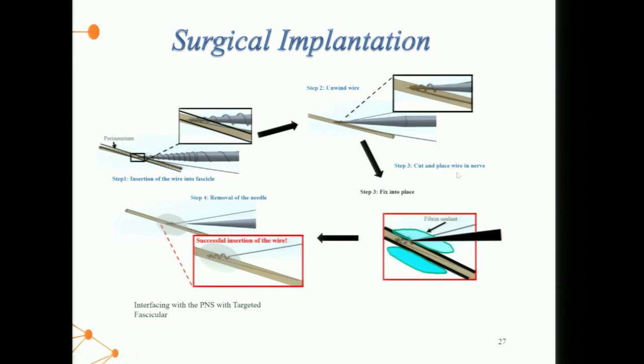Well, we came up with this idea. And at the time, I knew about a technique called microneurography. If you take a tiny needle, and a neurologist will do this, you take this tungsten, very sharp tip, about 2 micron diameter tip, and then place it, with no visual guidance, find a nerve, put it into your arm through the skin until they get into a nerve. They leave the electrode in there, it's called microneurography, and then they record action potentials passing through units, and they check the velocity, whatever, for diagnostic purposes. This is a fairly well-known diagnostic method, I should say.